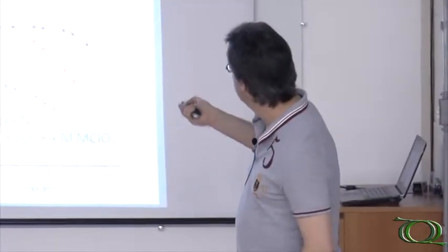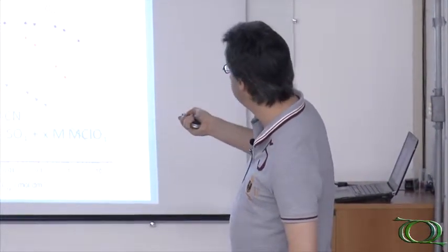Probably from this structure here, which we know only involves sulfate and water or hydronium ions, to some other structure where we have substituted the hydronium ions by the cations. And in this case here, in cesium, we also see an effect on these spikes. They go more positive, and the intensity decreases. We also see this with sodium and potassium, but we need higher concentrations. So again, we made the same thing. We plotted the potential of these peaks and of these spikes as a function of the concentration.